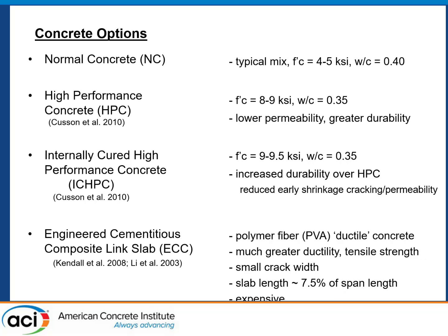Then for the concrete options, of course, we have normal concrete, one of various high-performance concrete mix designs, and an internally cured HPC mix. The advantage to this was, it was reported that this internal curing process helped to reduce the early shrinkage cracks, creating a less porous or less permeable mix to prevent the water and chlorides from penetrating to the steel. And then finally, there was one reported, an engineered cementitious composite link slab.